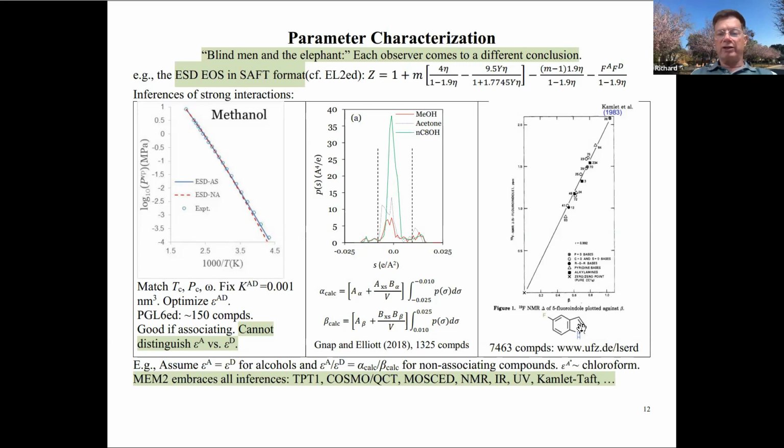Then we put this molecule in contact with, let's say, chloroform, at 0.5% of each, and measure the shift of this fluorine, this F NMR. Based on the amount of the shift, we can characterize, okay, chloroform is this amount acid, then the next acid and the next acid relative to that, based on how much this shift is. So that's the basis of this LSER theory.